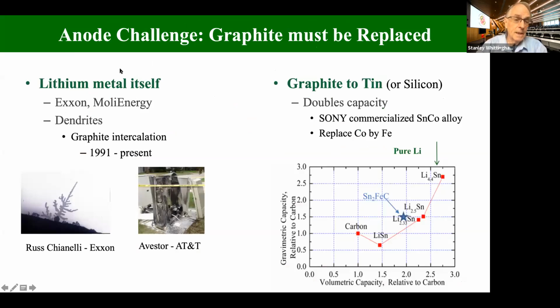So lithium metal itself was used in the first generation of the Exxon cells. Moli Energy went commercial. They used molybdenum disulfide instead of TiS2. They used lithium metal. And after a number of their batteries, which were used in the black boxes and the planes, almost brought the planes down, they stopped using lithium metal. But this is what happens.